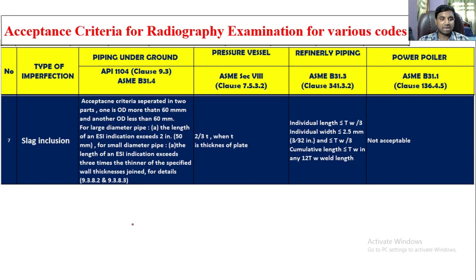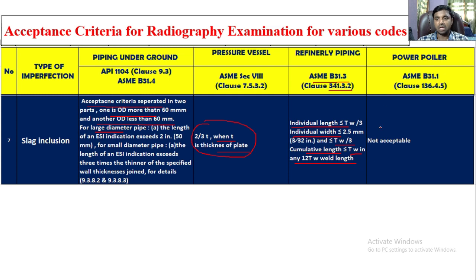Type of imperfection: slag inclusion. Acceptance criteria are separated into two parts — OD more than 60 mm and OD less than 60 mm. For full details, refer to clauses 9.3.8.2 and 9.3.8.3. For ASME Section VIII, slag inclusion maximum is 2/3T where T is the plate thickness. For ASME B31.3: individual length ≤ Tw/3, individual width ≤ 2.5 mm and ≤ Tw/3, cumulative length ≤ Tw in any 12T weld length — see clause 341.3.2. Power boiler: not acceptable.